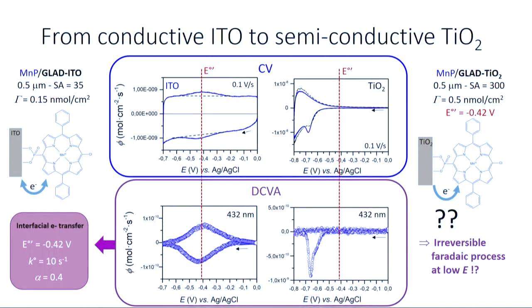And now you can see that the data we can record at the semi-conductive titanium dioxide electrode are completely different. It's not very obvious from the cyclic voltammetry that we indeed have a Faradaic current, if you compare the blue one, which is with the manganese porphyrin, and the black one, which is without. But from the DCVA, where we follow accumulation of the manganese 2 state, we confirm that we indeed have a reduction process. This reduction process appears first to be irreversible, and second to be significantly downshifted in terms of potential compared to the formal potential of the manganese 3, manganese 2 redox couple.